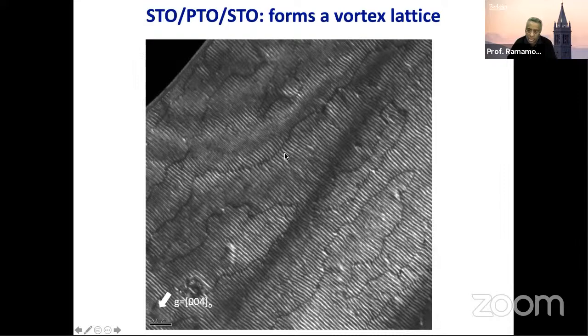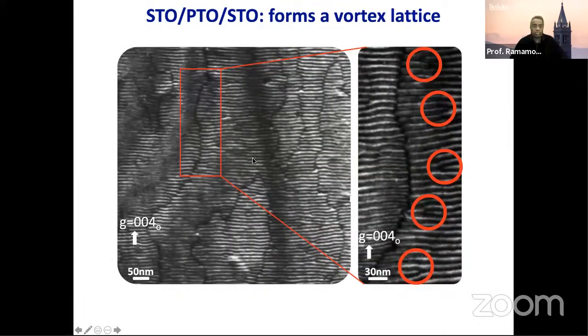So that length scale is of the order of 5 nanometers. But that's not all that you see. If you look at it, there are these boundaries. It looks like there are defects in the structure. It looks like there are other defects, which if you blow it up, you can see very clearly. That looks like a phase boundary or an antiphase boundary. But if you look at it more carefully, you can see that these red circles are highlighting dislocations in them.